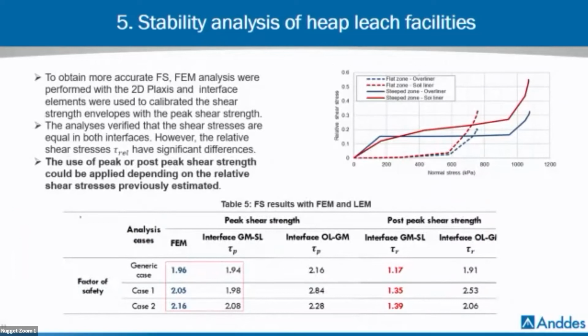To obtain a more realistic factor of safety, the analyses were performed with Plaxis. The interfaces of the heap leach overliner with geomembrane and geomembrane soil liner were modeled with interface elements using the shear strength envelope calibrated with the peak shear strength. The analysis verified that the shear stresses are equal in both interfaces. However, the relative shear stress has significant differences, as you can see in these graphs. The result demonstrates that the interface at the steps is particularly more susceptible to reach the failure limit, but the peak shear strength is not mobilized.